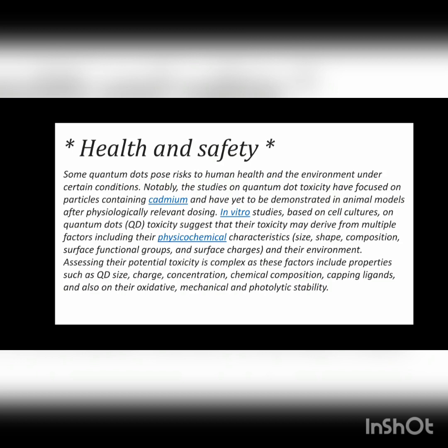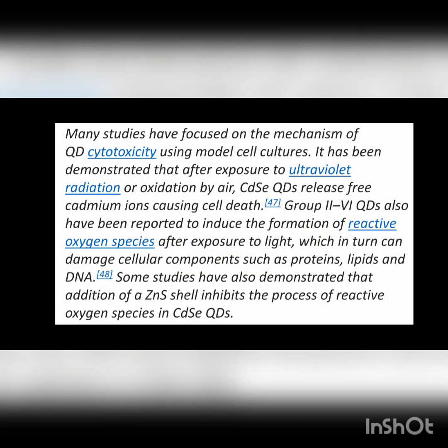Assessing their potential toxicity is complex, as these factors include properties such as quantum dots size, charge, concentration, chemical composition, capping ligands, and also their oxidative, mechanical, and photolytic stability. Many studies have focused on the mechanism of quantum dots cytotoxicity. Using model cell cultures, it has been demonstrated that after exposure to ultraviolet radiation or oxidation by air, quantum dots release free cadmium ions causing cell death.